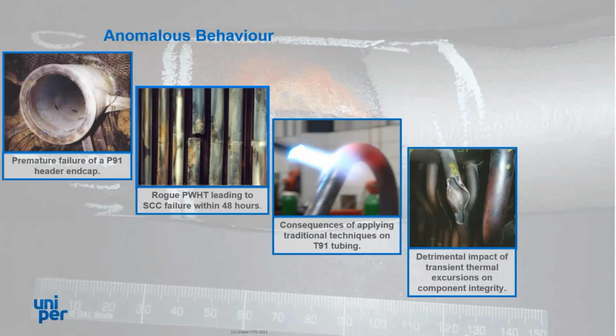We've also seen issues with combustion in some of the coal-fired plant, which has meant that the grade 91 tubing has seen transient temperatures up towards 700 degrees centigrade. Multiple events such as these have tended to rob the grade 91 material and taken it from the mechanical, the high temperature creep properties of a grade 91 down to a grade 9. What I've often described as rather like cutting Samson's hair. The material ceases to behave as it was intended and the result of this is premature creep failures, as highlighted in the illustration.